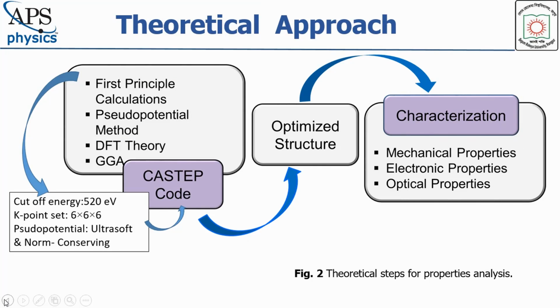Let's have a look at the theoretical approach. My research is based on computer simulation and investigating some important properties of perovskites. Here I have employed Materials Studio simulation software. I simulated cesium-lead chloride with cutoff energy 520 electron volt and K point set 6x6x6. I carried out these calculations using the CASTEP code.